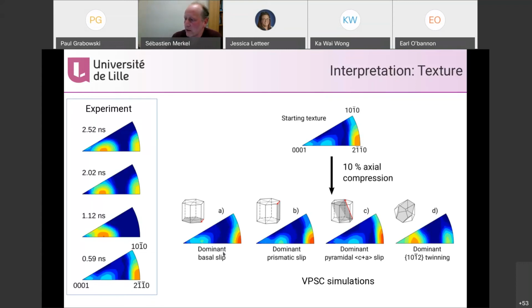If I run a simulation saying that texture is due to basal slip, this is what I get. If I say dominant prismatic slip is dominating grain orientation, this is what I get. If I say it's pyramidal C plus A, this is what I get. And if I assume that the dominant deformation mechanism is twinning, this specific type of twinning, which is common in HCP metals, 10-12, then I get something which is really close to what we see in the experiment.